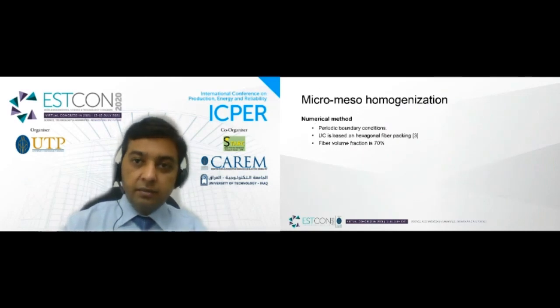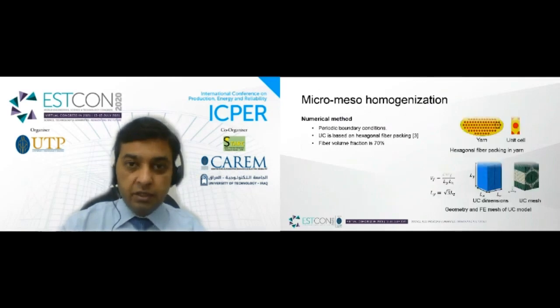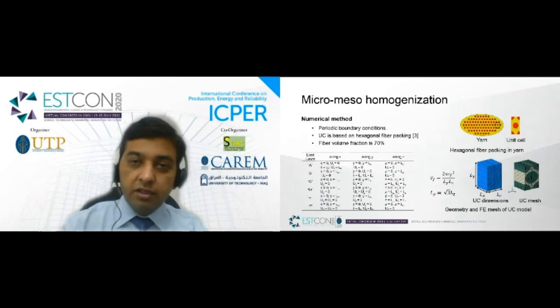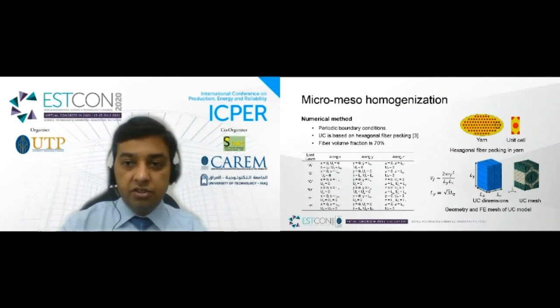Whereas the numerical method for elastic constant prediction of 3D composite is based on periodic boundary conditions. The periodic boundary conditions are applied on the unit cell model of impregnated yarn. The unit cell model assumes that the fibers are arranged in hexagonal packing in the impregnated yarn, whereas the dimension of the unit cell is determined based on the radius of individual fiber and the relationship between the geometric dimensions. The periodic boundary conditions were applied in the form of 6 load cases, 3 normal and 3 shear.